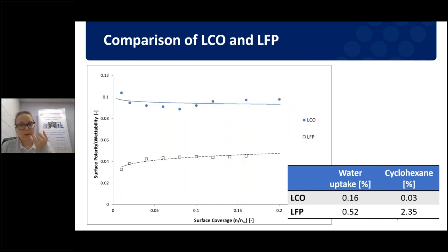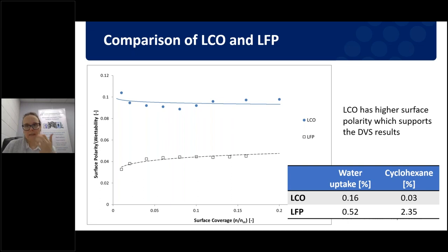This means that the LFP surface polarity and wettability are very low compared with the LCO. This is what we also saw in the DVS results, that LFP shows better sorption behavior with cyclohexane compared with the LCO, which seems to have higher water uptake than cyclohexane. So this supports the data we got with the DVS.